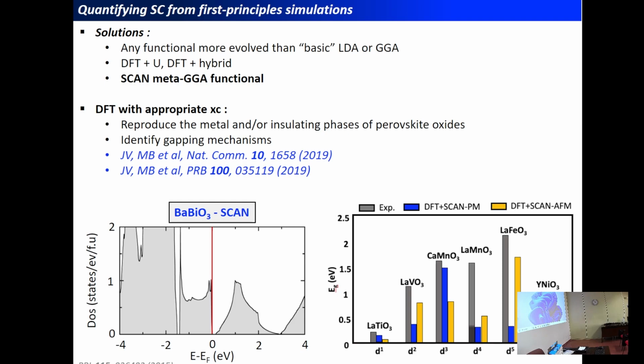But we have also shown previously that it's sufficient to reproduce the insulating character of several transition metal oxide perovskites with titanium, vanadium, manganese, iron, or nickel. In these systems, we can predict the insulating character with a magnitude of the band gap which is reminiscent of the experimental value, either in the antiferromagnetic ground state, but also in the paramagnetic phase.